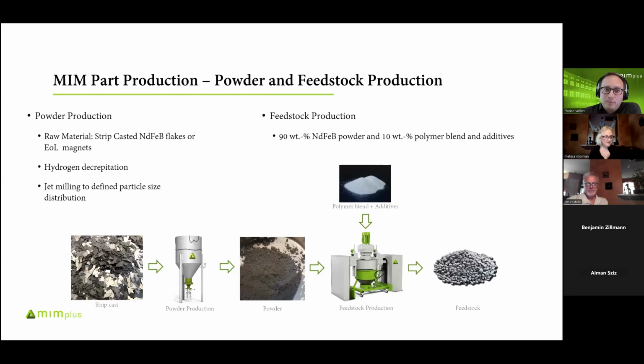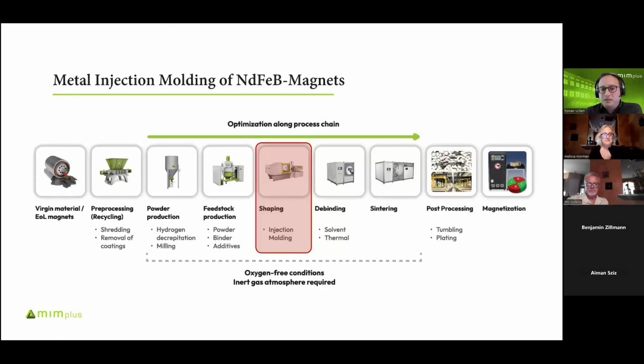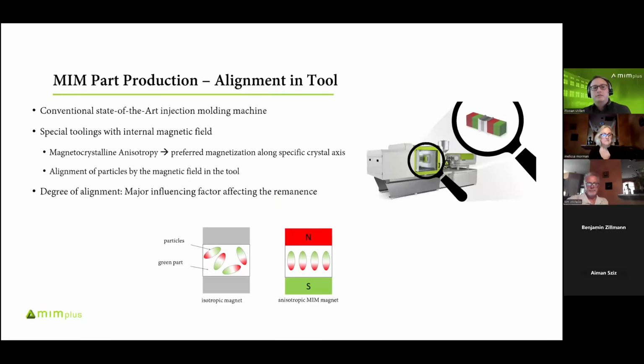The next step would be the feedstock production, and that's what's different compared to a press and sintered magnet. We take the powder, put it in a specially designed compounder, and mix it with a polymer blend and other additives in order to get our feedstock. This feedstock can then be used for the shaping process. Therefore, we use conventional state-of-the-art injection molding machines. And with our in-house tooling shop, we manufacture specially designed tooling that has an internal magnetic field.